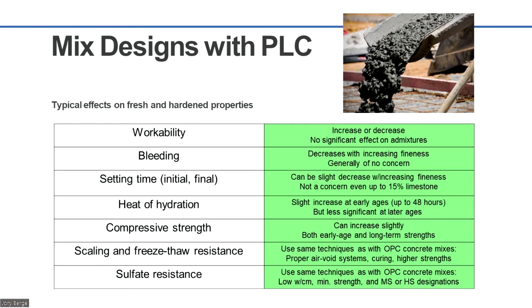The good news is overall, it's comparable to ordinary Portland cement. It may decrease your slump if it's ground much finer than your typical Blaines that you've seen in your regions. It may decrease your bleed, again, based on fineness, and it may speed up your set time, but it rarely delays your set time. So that's something to consider. And then depending on the fineness and the optimized blend, this could increase the hydration rate, and it may actually increase early age strengths, and depending on your curing, control your long-term rates.